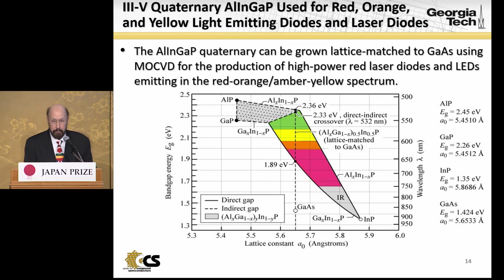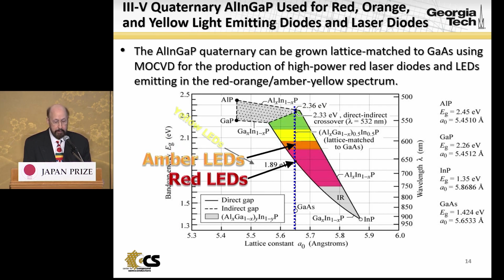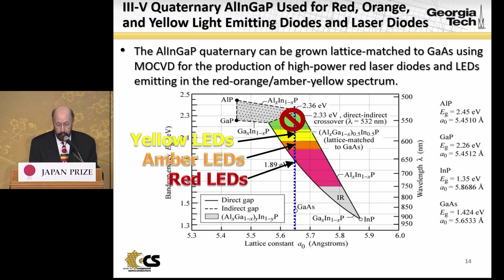Let me now turn to the next important event, which was, as I mentioned, the development of the quaternaries. This is the energy gap in electron volts versus lattice constant in angstroms for the quaternary aluminum indium gallium phosphide, which can be grown lattice matched to gallium arsenide substrates, as shown by this vertical line. Materials along this vertical line can be produced in high quality on gallium arsenide substrates and are used currently to make high brightness red LEDs, amber or orange LEDs, yellow LEDs, but it cannot be used to make green LEDs because of the proximity of the indirect band gap section of this quaternary alloy shown here in the dotted area. So we have to turn to another material to make green and blue LEDs.